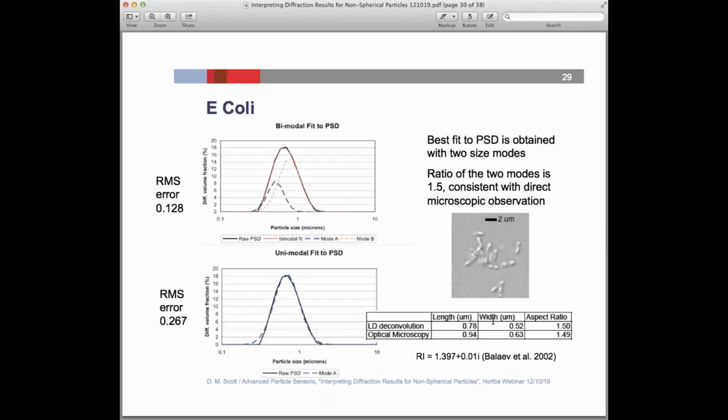The problem is these particles are breaking in two, as you see here, and some of them get quite long, and then they're reproducing. So depending upon where you catch them in their life cycle, you might see two smaller little ellipses, or you might see a longer rod. So it makes the measurement a little bit complicated, and I have to say that the statistics on this aren't all that great. A lot of people would look at this PSD and say that was a single mode, which would be my preference, to call that a single mode.